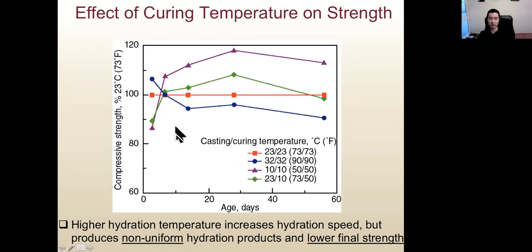All right, so the red line is the concrete casted and cured at room temperature, around 70 degrees. The blue line here is we cast the concrete and cure the concrete at 90 degrees Fahrenheit. So compared with the red line, the early age strength, which is the strength for the first week or so, will be higher.